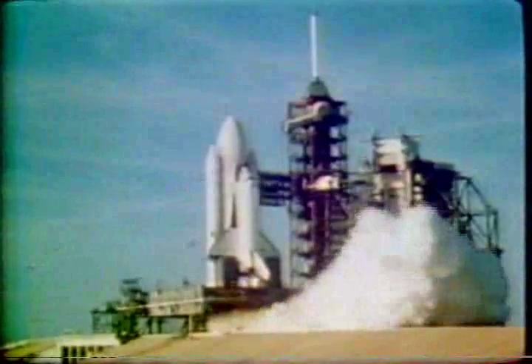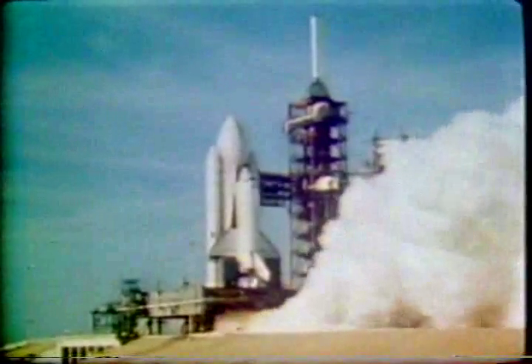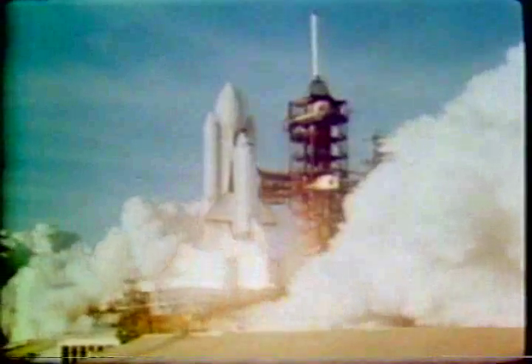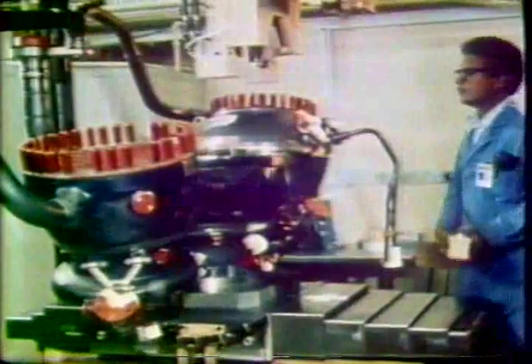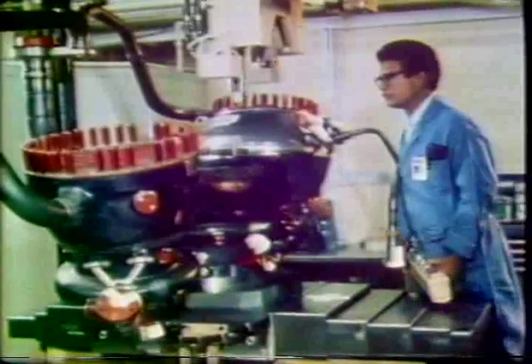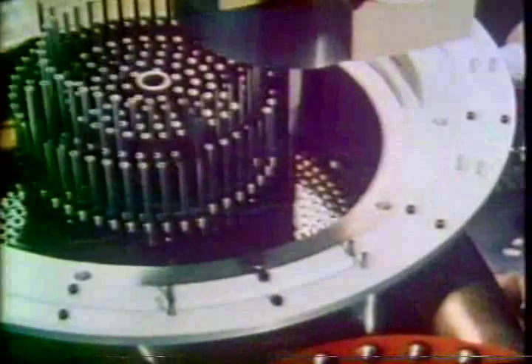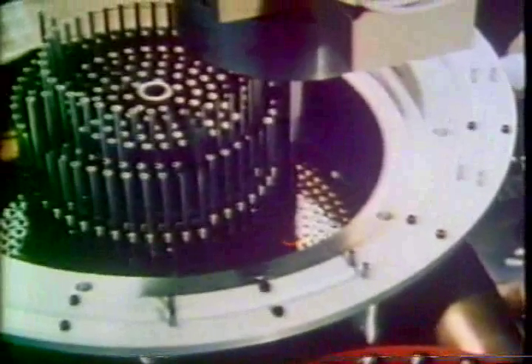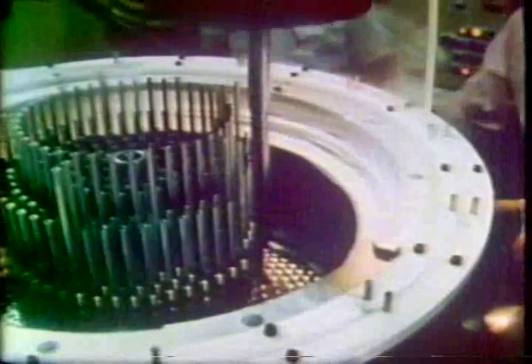Nearly every aerospace manufacturer in the free world employs inertia welding in the manufacture of components. The F-14 fighter bomber uses several inertia welded parts. Manufacturing Technology built the welder for the Rocketdyne division of Rockwell International, manufacturer of the Columbia's engines. Inertia welding was found to be virtually the only practicable method of welding the 600 closely grouped injector posts on the mammoth main engines of the Space Shuttle Columbia. Each weld of the cobalt-based alloy posts to the Inconel 718 stubs was accomplished in less than 5 seconds.